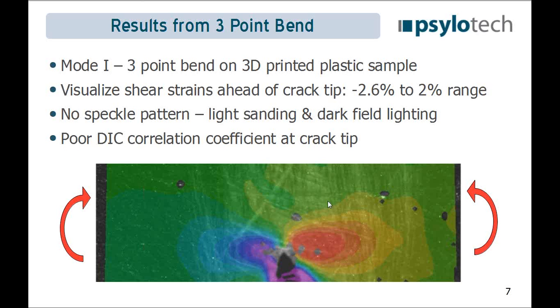It turned out to give pretty good results in that we were able to see the strain fields ahead of the crack tip. In this case, these are the shear strains in front of the crack tip, in a mode 1 opening. So it's quite an interesting result. If you don't have digital image correlation, it's hard to see.